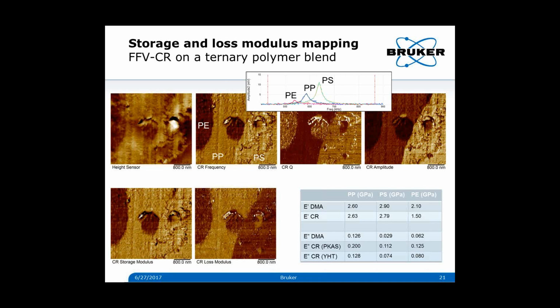Finally, getting back to the ternary blend that we looked at with PeakForce QNM and Dalia talked about, we can do this in contact resonance also. You start out with these resonant sweeps, and you can see they're nicely differentiated in frequency. And here's their frequency map, or Q map. The amplitude actually shows a very nice contrast as well, and those can be used to calculate storage and loss modulus. If you do the calculations for the storage modulus, you compare them to DMA at the same frequency.